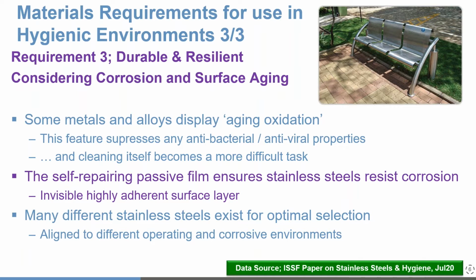environments. So if that aging oxidation feature occurs, it suppresses any antibacterial or antiviral properties that the material may possess, and cleaning itself becomes a more difficult and intense task. Again, one of the benefits of stainless steels is that they have this invisible self-repairing passive film that resists corrosion and is highly adherent to the surface layer, which makes cleaning and disinfecting much more straightforward. And on top of that, many different stainless steels exist, which allows users to select the optimal choice of material for the operating conditions and any corrosive environments that exist in those operating environments. So stainless, again, is a good fit against this notion of durability and resilience.